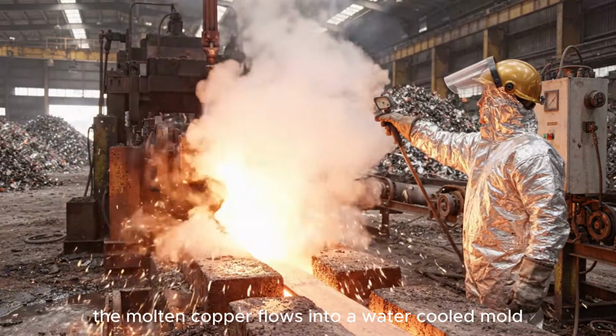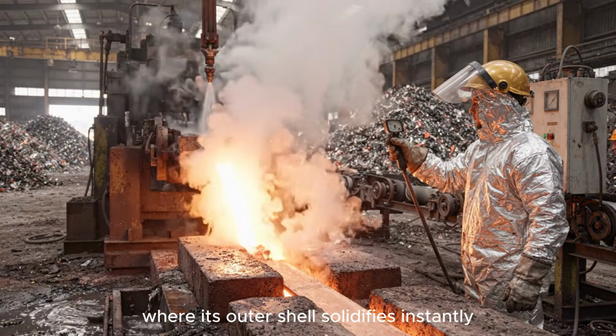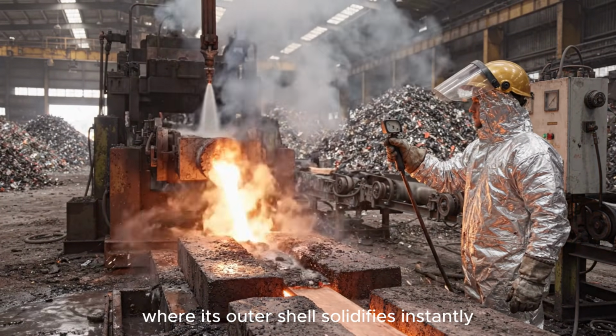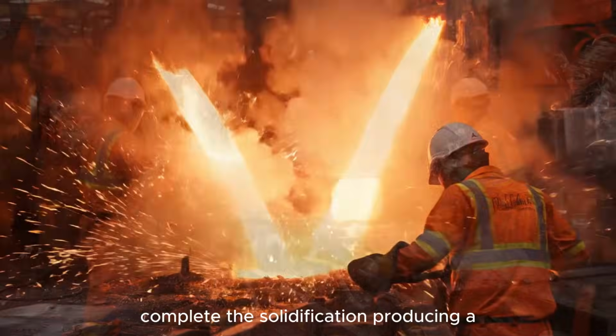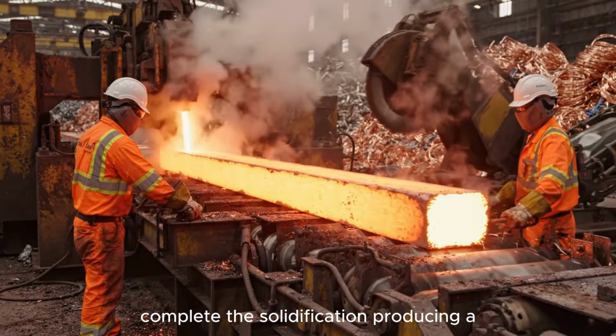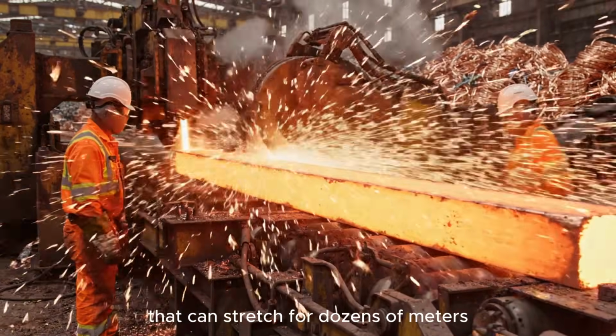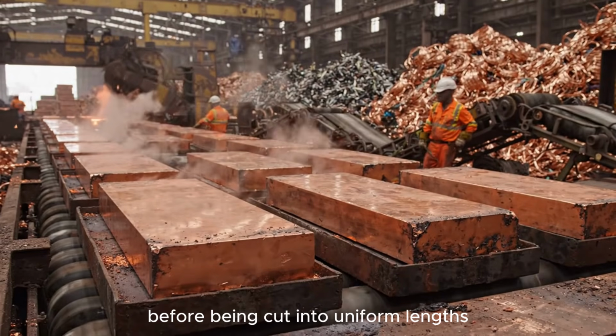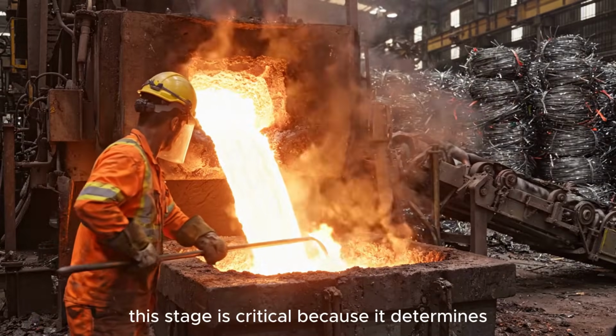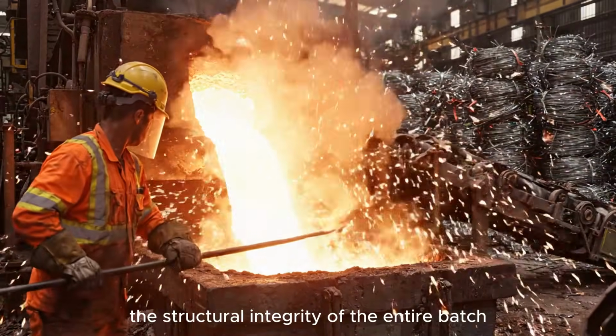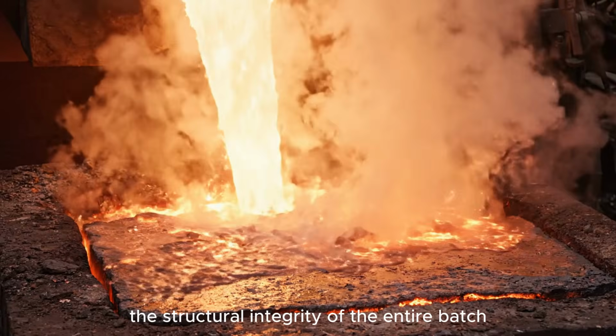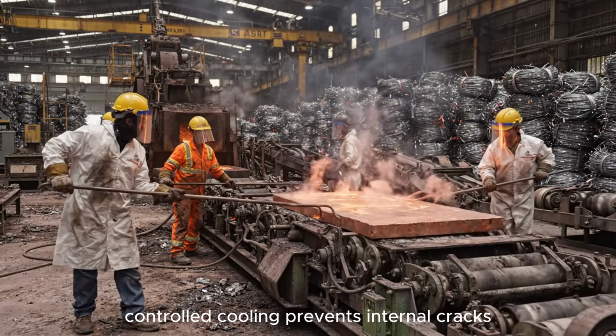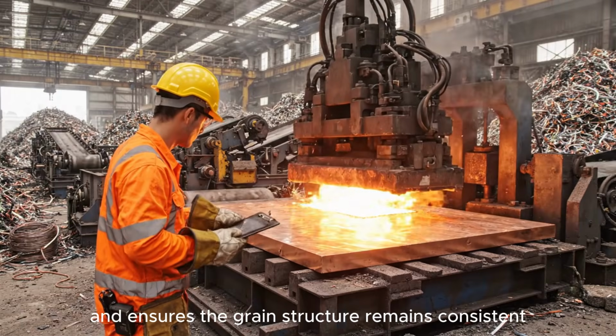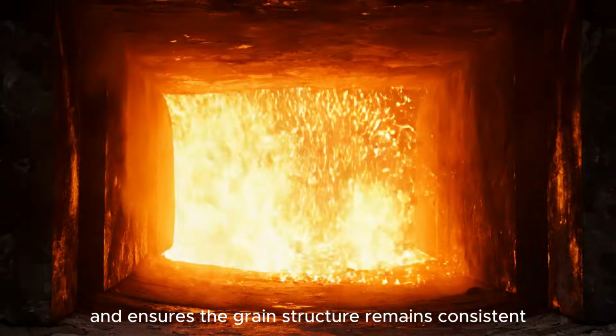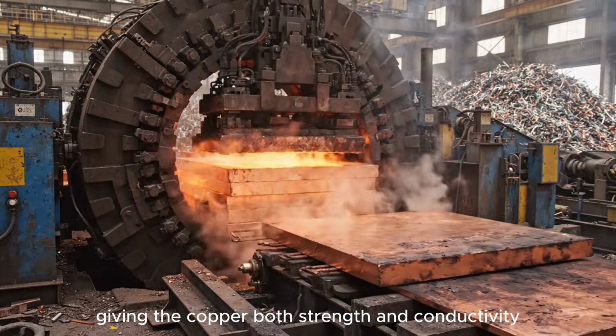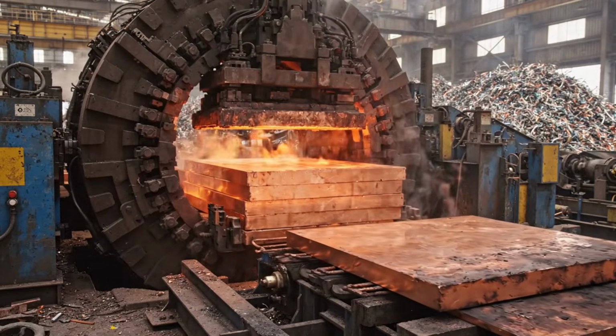The molten copper flows into a water-cooled mold, where its outer shell solidifies instantly, while the core remains fluid. Cooling then completes the solidification, producing a continuous bar of copper that can stretch for dozens of meters before being cut into uniform lengths. This stage is critical because it determines the structural integrity of the entire batch. Controlled cooling prevents internal cracks and ensures the grain structure remains consistent, giving the copper both strength and conductivity.